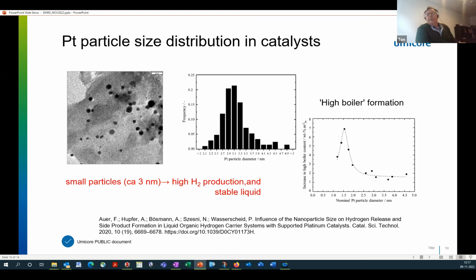And in the graph to the right, you see that the high boiler formation is very much dependent on the platinum particle diameter. So this is also something we have to compromise. So we want to have very small particles for the activity, but we don't want the oil to break too much. So for platinum, this turns out to be an optimal particle size of around 3 nanometers on the support.